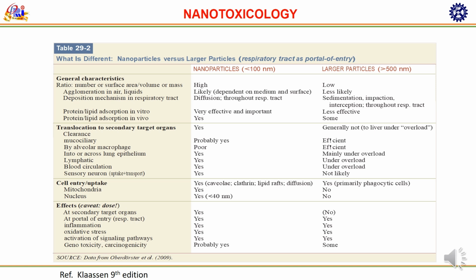Deposition mechanism in the respiratory tract. Nanoparticles move by diffusion and can deposit throughout the respiratory tract, including the deep alveoli. Larger particles deposit mainly by sedimentation, impaction, and interception, usually in the upper airways. Protein and lipid adsorption: nanoparticles strongly adsorb protein and lipid, both in vitro and in vivo, forming a protein corona that defines their biological identity. Larger particles adsorb fewer biomolecules and this process is less biologically significant.